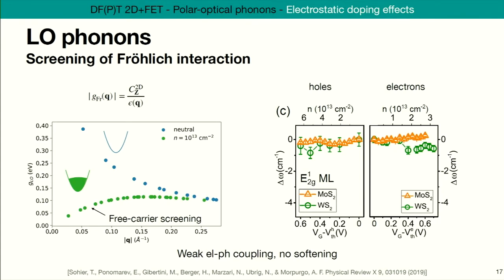So what happens here, and we can simulate all this, we can plot the coupling to this longitudinal optical mode as a function of the momentum, either in the neutral material, and we see here this increase as we go to small momenta, or in the doped material, and in the doped material you see this decrease, even this complete vanishing of the coupling at zero momenta. And this is due to free carrier screening, so screening from those added carriers. So weak electron-phonon coupling at small momenta, no softening, and the frequency is more or less constant. So we understand why this is the case.